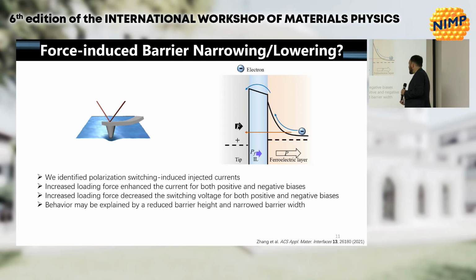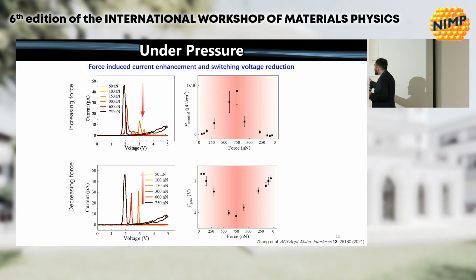So I think I went over that a little too quickly. So here, this is going up to 1 to 10 to the 5 microcoulombs, and we would only expect for bismuth ferrite to have, depending on the phase, on the order of 100 microcoulombs. So it's orders of magnitude higher, and even if we took that the area of contact was much larger, it would still be orders of magnitude higher. So we don't think it can be the displacement current itself. It has to be related to some charge injection.